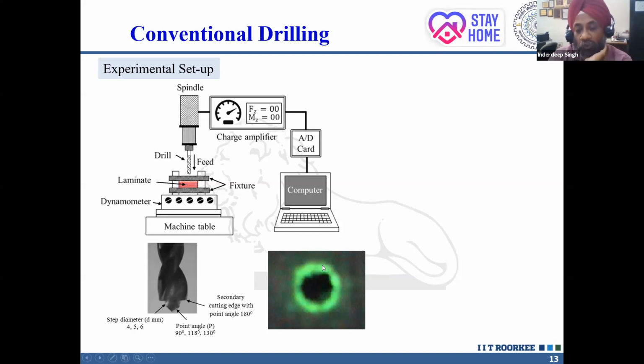And one of the damaged holes you can see here, this is a damaged hole. Actual hole would have been somewhere here, but this is a non-destructive dye penetrant testing image of a hole with fluorescent dye, which glows under the ultraviolet light. This technique, when I was working at IIT Delhi, we tried different methods of quantifying this damage area, but finally this was the best method that we were able to develop. So we took images of the holes made with different speeds, different feed rates, different drill point geometries, different hole diameters, and different conditions, and then each and every hole was tested using the non-destructive dye penetrant testing under the ultraviolet lamp.